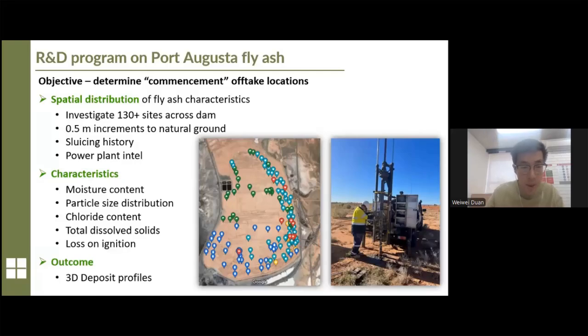Based on that, we started our R&D program, which currently has two stages. The first stage is to understand the fly ash characteristics, especially the spatial distribution. To achieve this, we investigated 130 sites across the dam, as shown here. For each site, we drilled holes, taking samples at 0.5 increments until reaching the natural ground. We also reviewed the sluicing history and power plant information to gather as much knowledge as we could to harvest the fly ash here.